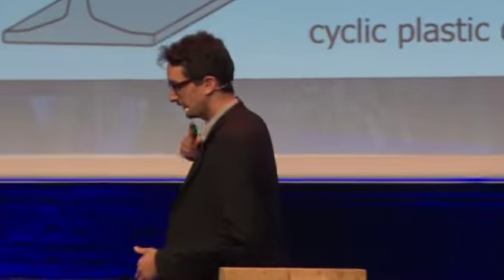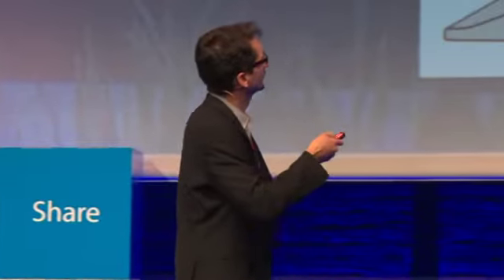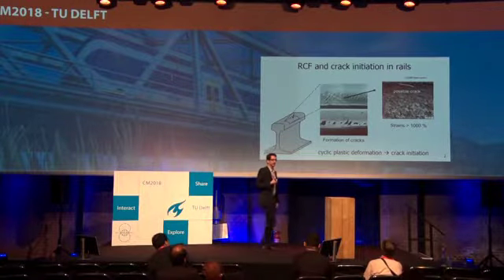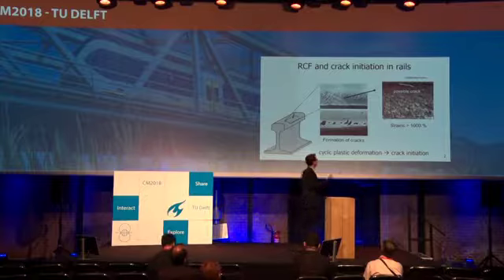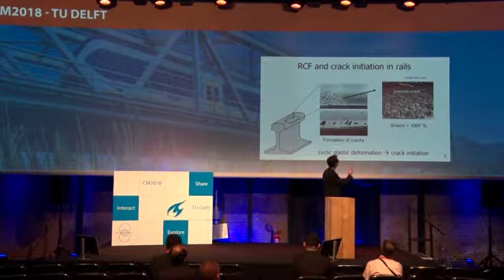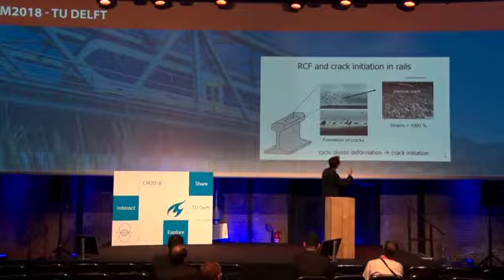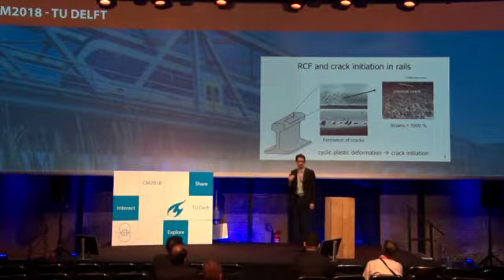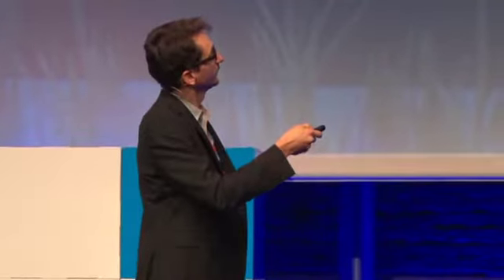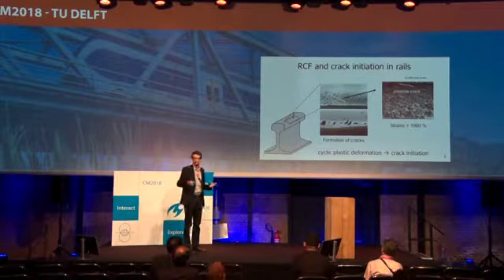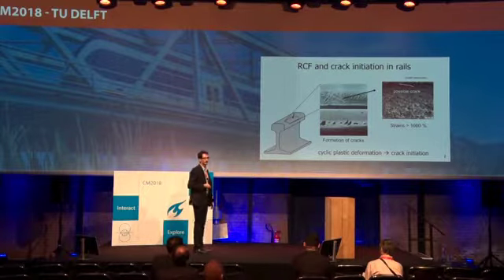So basically, we think in Leoben in our group that the cyclic plastic deformation that occurs in a rail has much to do with crack initiation, but also the crack paths. If we have a shear deformation field like that in the rail surface, those trajectories of the deformation more or less define also where the cracks will be. On the other hand, when we reach a certain shear strain up here, that might also be an indicator or even a damage criterion. I think if we talk about ratcheting and failure due to ratcheting, that's something like that.